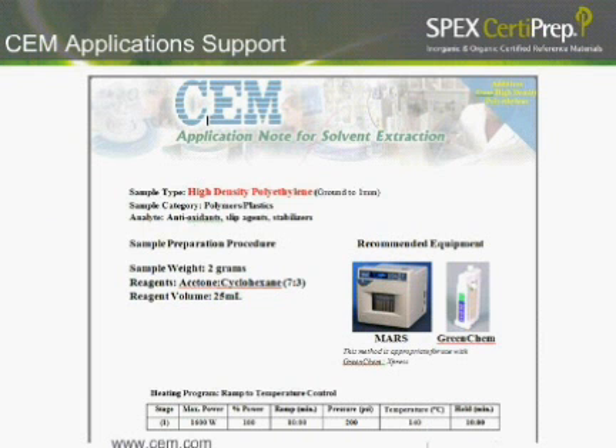You can see here we have an application note for one of our polymers. We have many application notes available depending on the type of polymer you're interested in extracting. An example here is high-density polyethylene. You can see here that the application note gives you some good starting recommendations for the conditions that you'll need to get a good extraction. For example, in this application note, a good starting mass for the high-density polyethylene is 2 grams. In terms of reagents, we recommend using an acetone cyclohexane in a 7:3 ratio. In terms of the volume, 25 mils is a good starting volume.